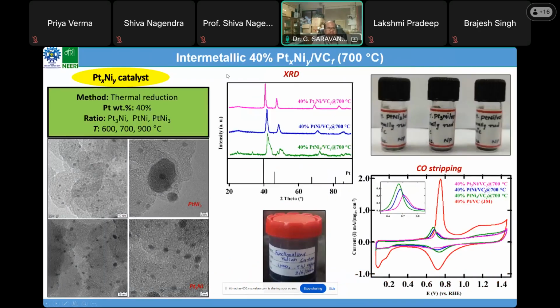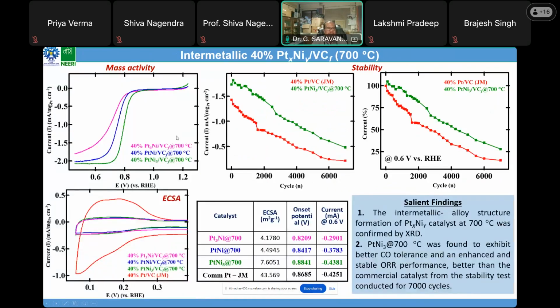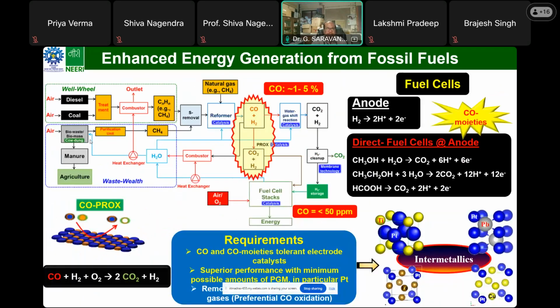Another combination tried in the lab uses Pt-nickel, and again, the same story. When you keep nickel or cobalt in the lattice of platinum, it shows much better performance than the commercial Johnson-Matthey platinum catalyst. Here we performed up to 7,000 cycles, showing much better durable performance compared to the Johnson-Matthey catalyst.